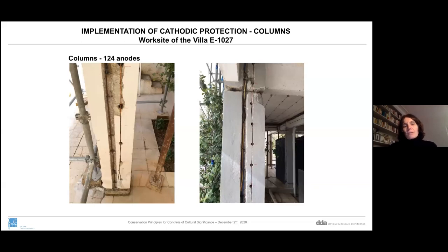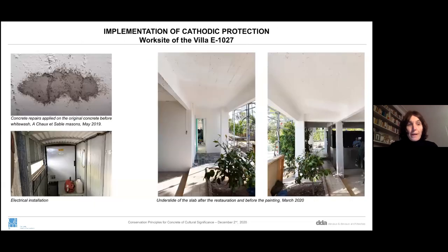At the end of this restoration program, we had to repair the concrete with a formulated concrete, which was identical to the historical one, so that it fits very well. And you see the electrical installation cupboard, a little cabin where we put the electrical installation, and all the cables arrived there. In the end, you have the two pictures. You don't see any intervention of the cables. They are all put in the concrete in the repairs. This is what is now finished. And we had the big chance that the building is whitewashed, so you don't see anything anymore. Thank you.